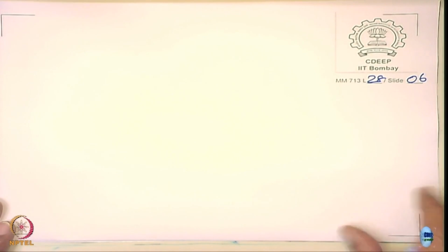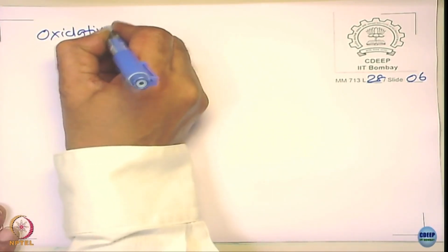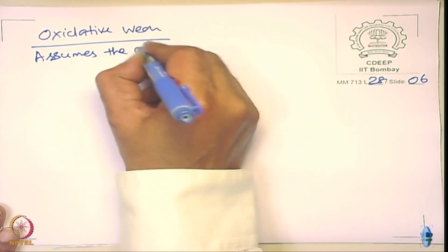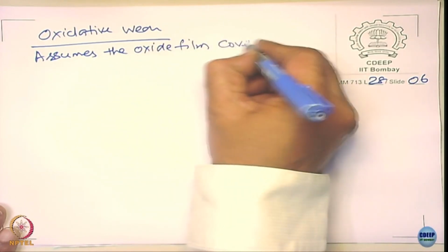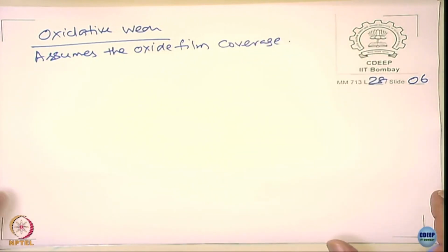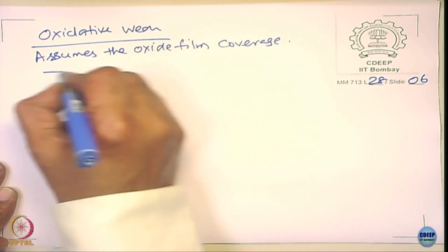The other mechanism is oxidative wear. It assumes oxide film coverage, and rightly so, right? Most engineering materials and engineering alloys are prone to oxidation at room or ambient temperatures, and so you can visualize a similar thing.